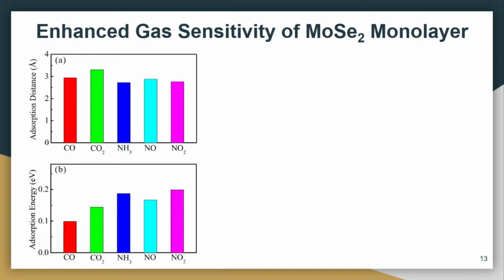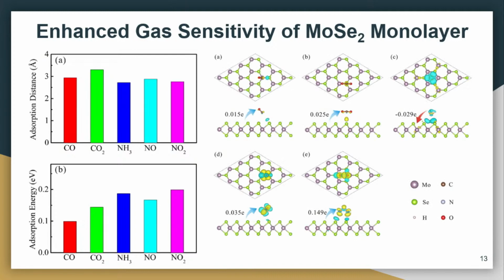So that was replicated here also. If you calculate the adsorption energy, NH3 and NO2 have a higher adsorption energy compared to all other molecules. Especially when you see this figure, we can understand this. The monolayer of molybdenum selenide has higher sensitivity to NH3, NO, and NO2 compared to your CO and CO2, right? Because for CO and CO2 the adsorption is so less, and the bond distance is also comparatively higher compared to all other molecules. So what we can say is your monolayer MoSe2 has very high sensing properties for nitrogen-containing gaseous molecules.